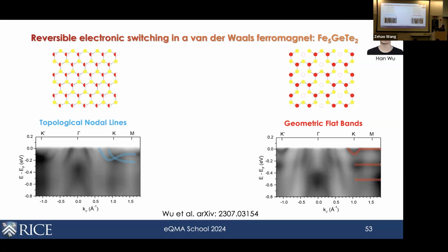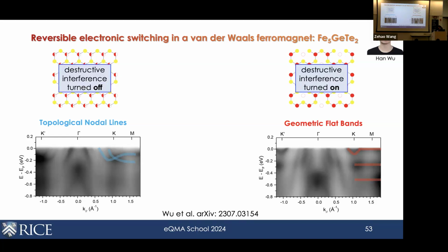And in this case, there are some symmetries that are broken that lift the Dirac points. Instead we see these flat bands in momentum space, which we understand to be associated with the switching on and off of this destructive interference. So this paper has the details of how we actually do this.